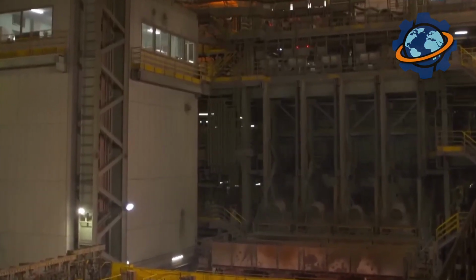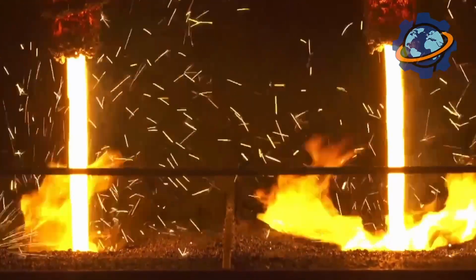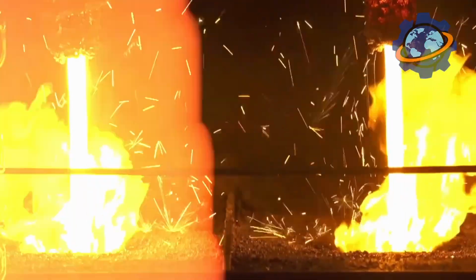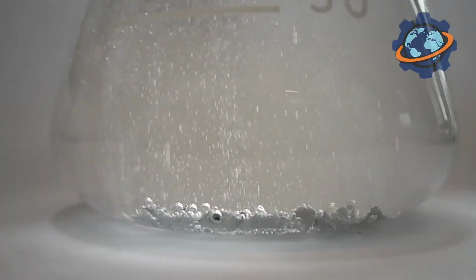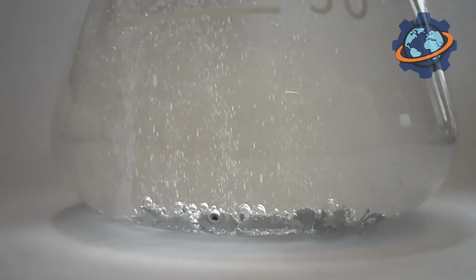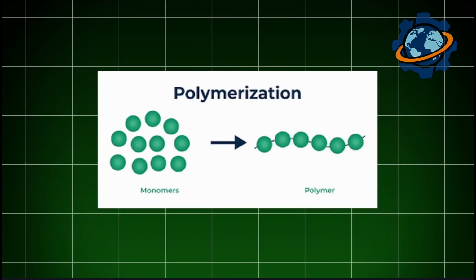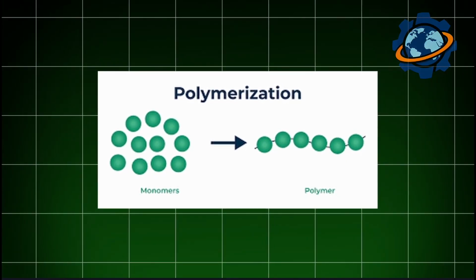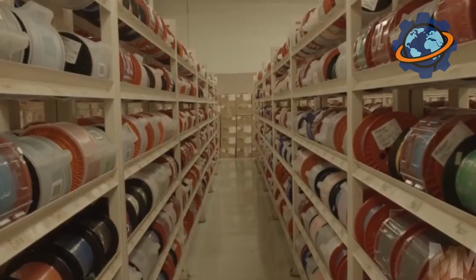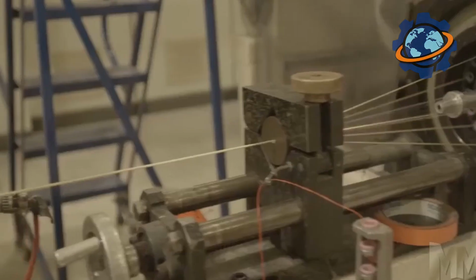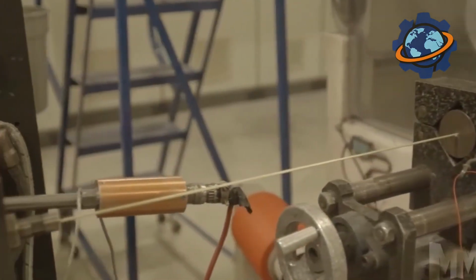First, the die, like a press, squeezes out all the excess resin, leaving only the necessary amount. Second, it tightly compresses all the fiberglass strands together, forming a perfectly round rod. Third, the heat from the die initiates the initial stage of the chemical hardening reaction, or polymerization. The resin begins to transform from a liquid into a gel. At the exit of the die, we can already see the familiar shape of the rod, but it is still soft and vulnerable. But how does it get its famous ribbed surface to hold well in concrete?